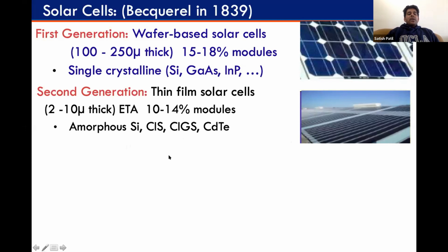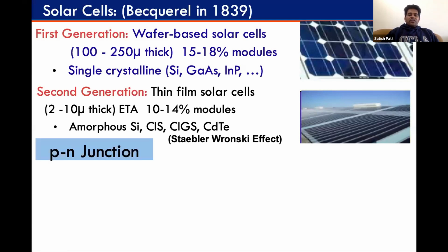Because soon after you convert from single crystalline to amorphous silicon, the material becomes a direct band gap, and you can harvest more light. But they did not match in terms of lifetime, because there was an issue with something called the Staebler-Wronski effect. If you keep on shining a light on amorphous silicon, the dangling bonds between silicon and hydrogen get knocked out, and you have a poor lifetime.